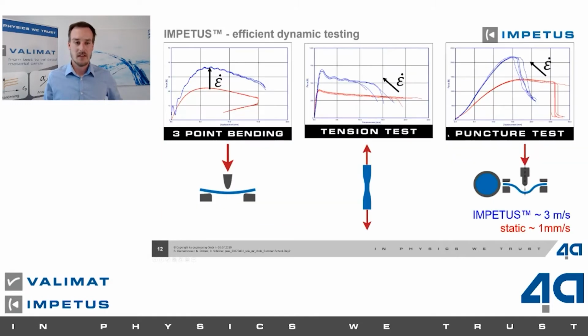Okay, and the last slide today is just our results from a 3-point bending, a tension test, and a puncture test, where we combine in blue a dynamic test from IMPETUS and a static test from any universal testing machine. And this slide shows you the big advantage of the dynamic tests with IMPETUS. These results are from a thermoplastic material, and it's a really typical thermoplastic result.